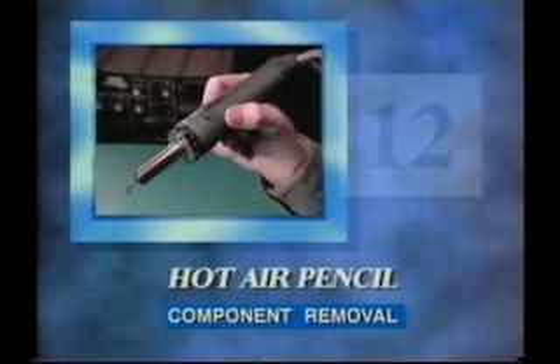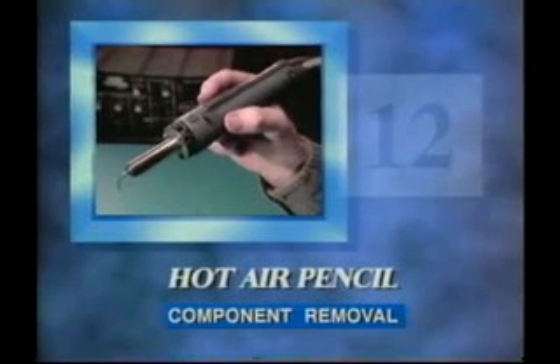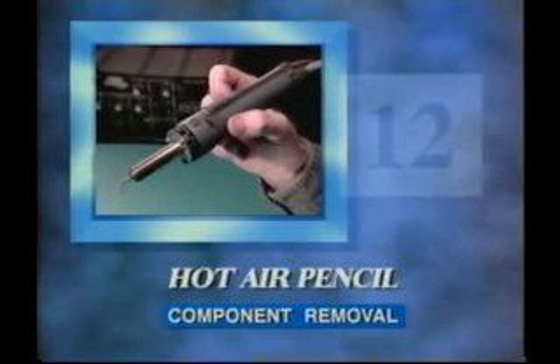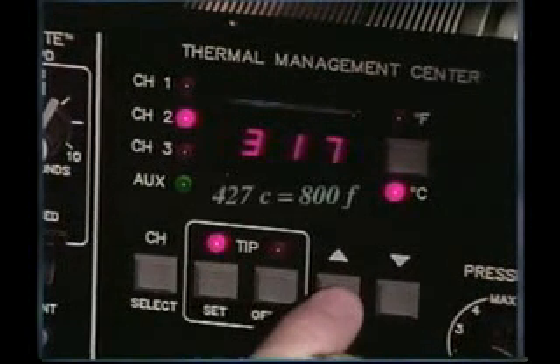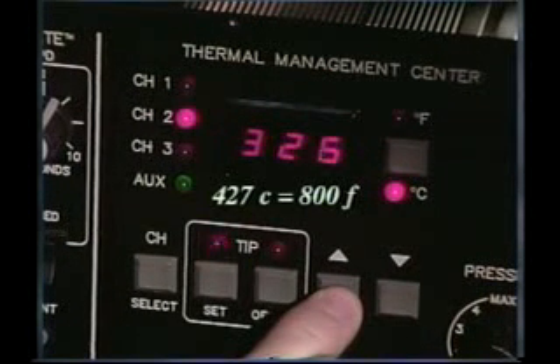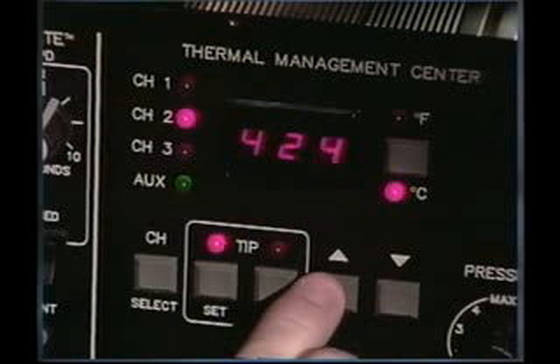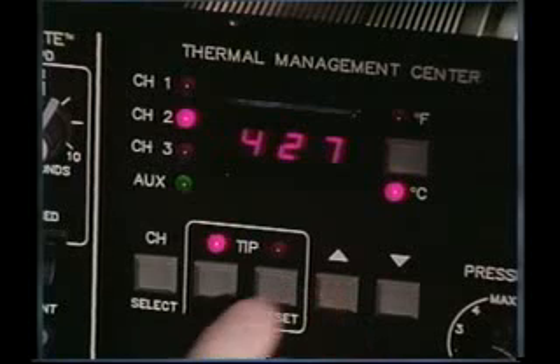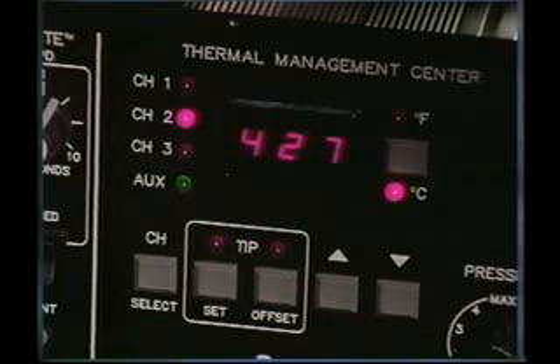In this section, we're going to review the chip removal and replacement operations using a hot air pencil. Let's begin by setting the temperature of the air to 427 degrees C. This may seem hot, but keep in mind that the exit air is always much cooler than the set temperature. Think of this tool like a home heating furnace, where the gas burns inside at around 300 degrees C. The hot air that comes out of the vent will only be slightly over 50 degrees C.